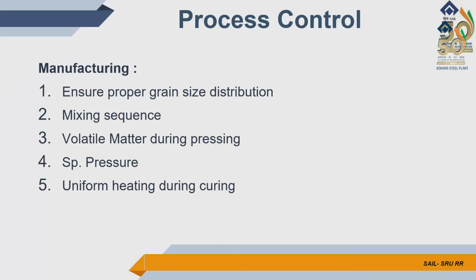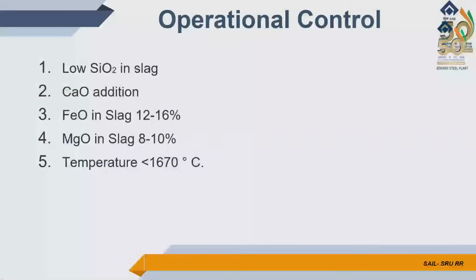Specific pressure during pressing is also important. 2 is the norm. The higher, the better. Increasing specific pressure decreases the porosity, increases the strength, CCS, and the bulk density of the brick. Also, during heating, you have to take proper care so that bricks do not burn.